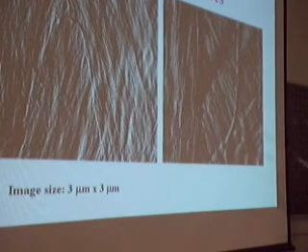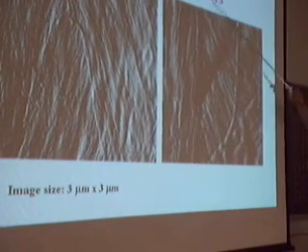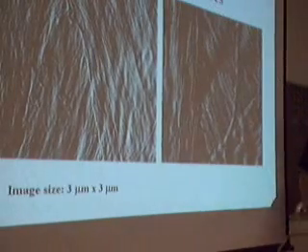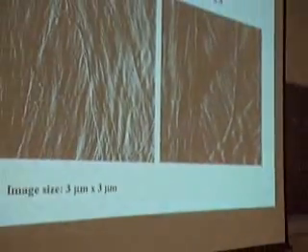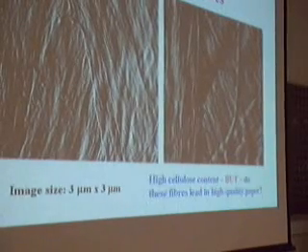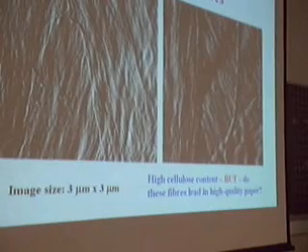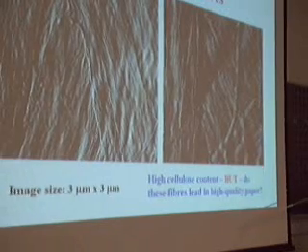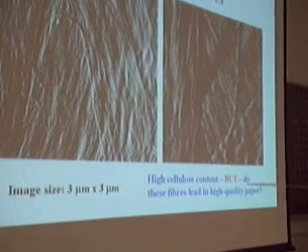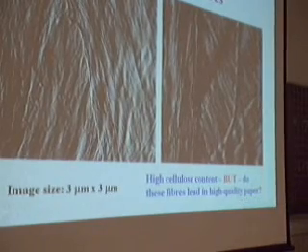But then, if you take a look at samples taken from the mechanical pulping, for example, we see that the process has been very successful in that sense, because what we see here is pure microfibrils, cellulose microfibrils, that are the small structural components of the cellulose fiber. Very small structural units, only 20 nanometers in diameter. And we can see different lamella there, and so forth. But actually the question that should be stated here: we have a very high cellulose content in these samples, but is this then enough to guarantee high quality paper?